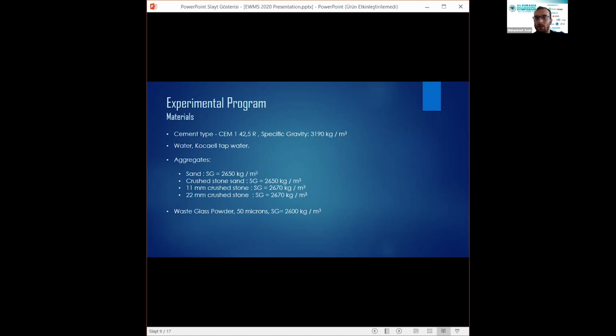And we use waste glass in powder form because if you want to see a pozzolanic reaction in your concrete, the waste glass's grain size must be closer to cement grain size. 70% of our waste glass has a grain size smaller than 50 micrometers, and our waste glass powder specific gravity is 2.6 tons per cubic meter. As you see, the lightest component of our concrete is waste glass powder, except water.